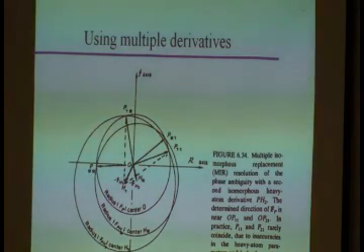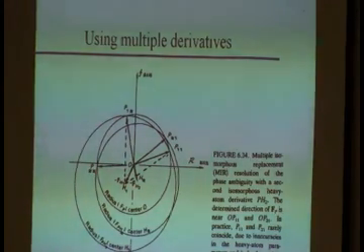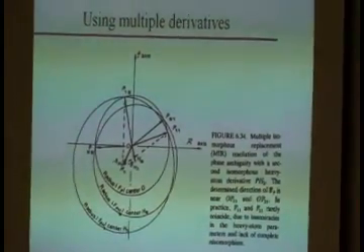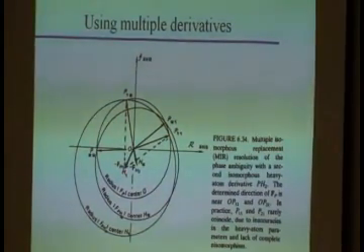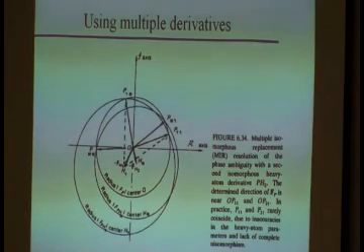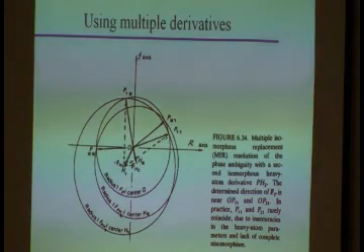You have your circle FP around 0, minus FH1 in this case. We had to designate somehow that it is the first one. You draw a circle around here, radius FPH1. Then you do the same a second time. There's your minus FH2. Then you draw a circle with radius FPH2 around the tip of this vector.